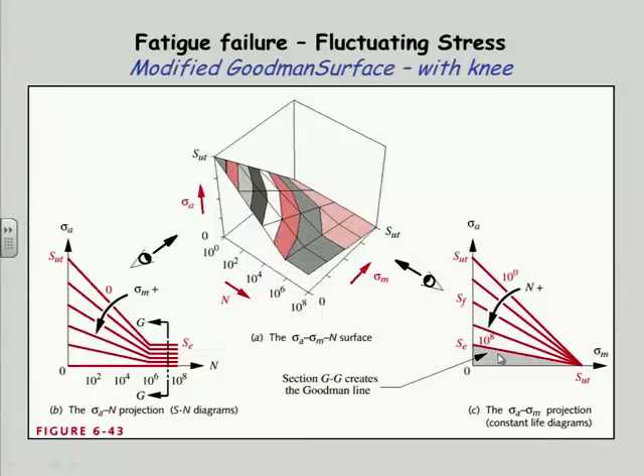So looking in this way, I'm looking at the alternating-mean plot on which I can draw the Goodman lines. So these are all Goodman lines. I'm sorry, I'm calling them constant life diagrams here. But in fact, it is the Goodman line as well, because I have alternating stress on this axis and mean stress on this axis. See sigma A, sigma M. So they're also called constant life diagrams because each of those is taken at a different level of N. Okay, so one of those is at 10 to the 8th, and that's 10 to the 6th, I guess, 10 to the 4th, 10 to the 2, and 10 to the 0. So obviously, as I have fewer cycles, my fatigue strength is better and better and better, and if I have one cycle, it's the SUT. That's not a fatigue case at all. That's just static loading.